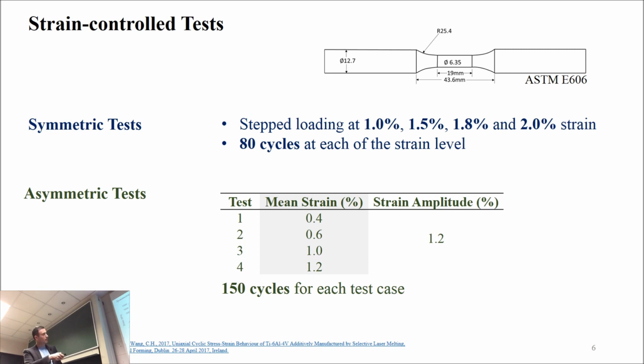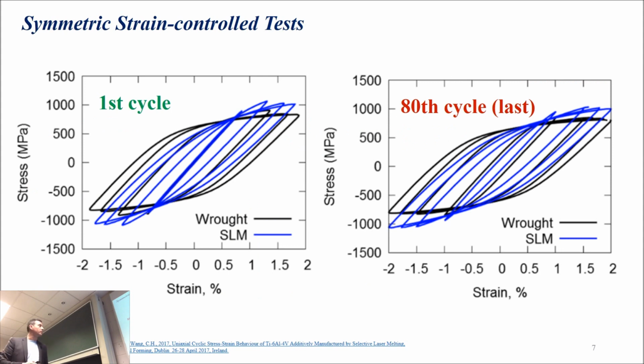So the wrought is the black line and the SLM is the blue line. If someone would like to see it more evidently, because this is a rather confusing graph, as always, we have seen that in the literature, but it's not ideal, if you'd like to have a better look. So what we did is we decomposed this array of different hysteresis loops to each one for each strain level. Here we see, for example, at 1% of strain level, the last cycle, and so on. What evidently comes out of these graphs, out of these strain curves, is that the SLM material has less capacity to undergo plastic deformation.